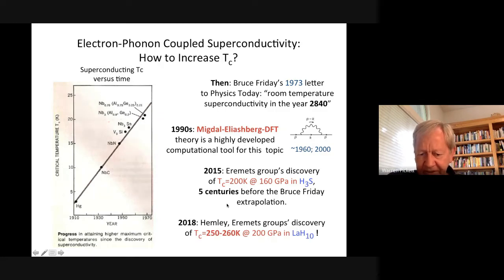And then in 2018, Russell Hemley's group in Chicago discovered, in what turned out to be lanthanum hydride LaH10, a TC of 260 Kelvin at 200 gigapascals, and this was pretty quickly reproduced by Eremets, who found in their sample 250 Kelvin, the same sort of data.